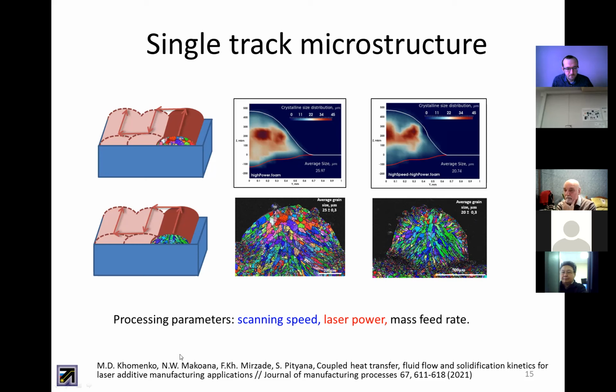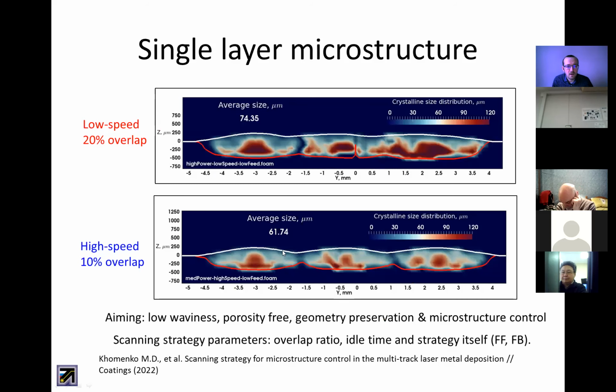We published this paper already recently, and we are now working on the single layer microstructure, where we also managed to show the microstructure control while preserving the layer geometry. So we've got an increased average grain size at low speed and a decreased one at high speed. This paper is almost ready, but it's not finished. We have some minor problems with that, but still we've got these in layers.